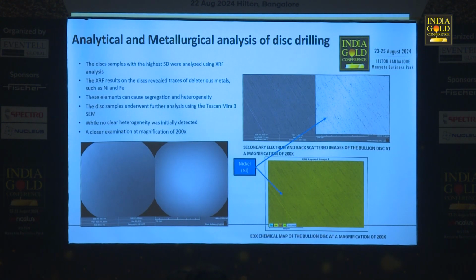We took the discs with the highest standard deviation. Then we noted that there were traces of iron and nickel in them. And then we used the scanning electron microscope, but when you looked at it, there was not much to see as to whether there was any micro heterogeneity or any segregation. So we used a magnification of 200 times with EDX, and that's what we saw: there was nickel present in the product.